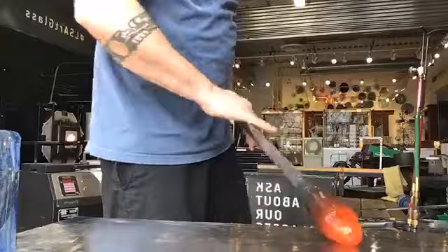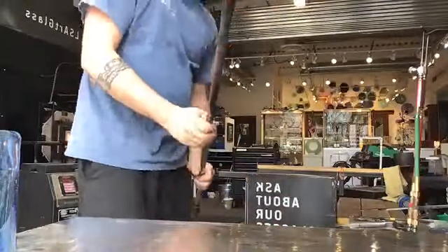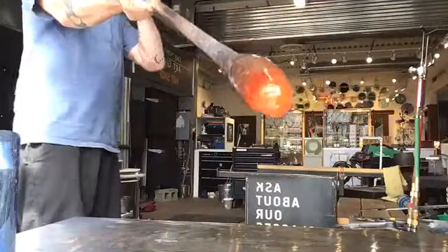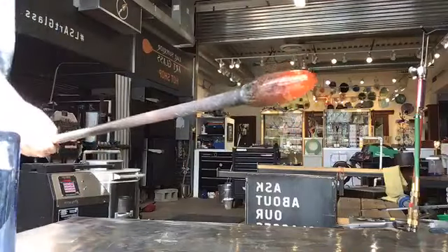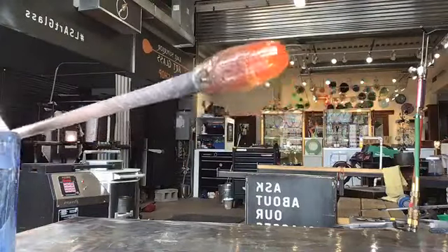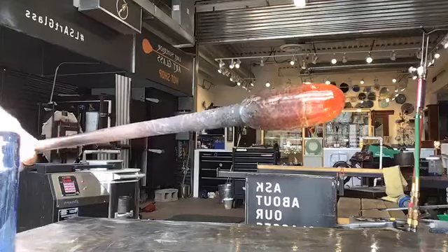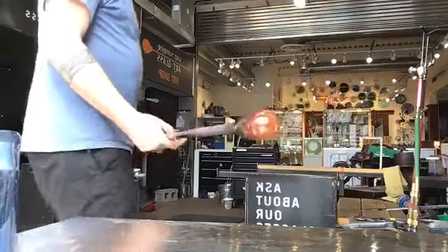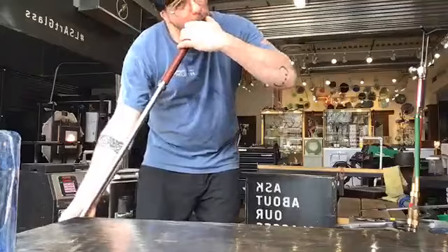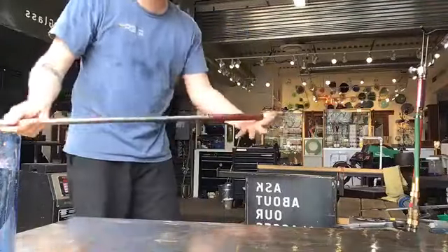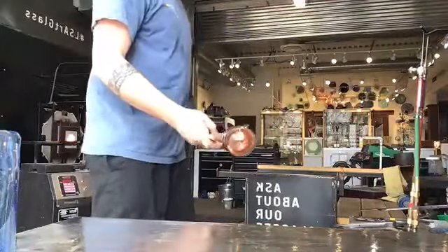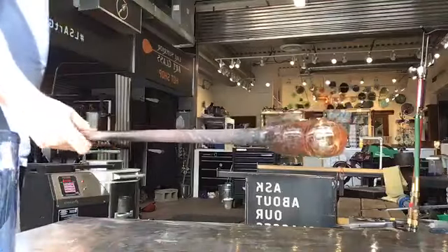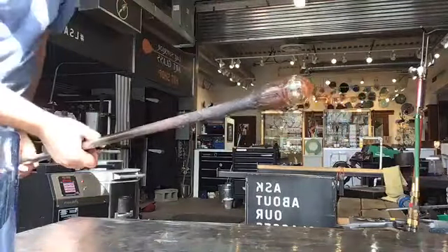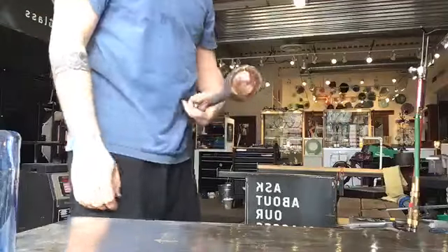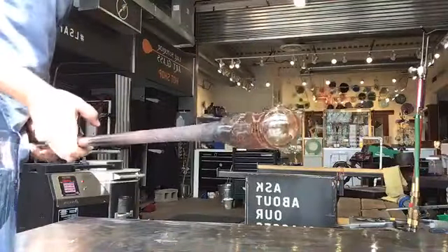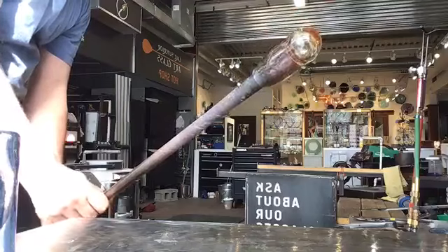Nice shape, nice and even. Go ahead and blow and cap. Should be able to see that bubble coming through the glass. I plugged. So the way I did that is I blew into the pipe and trapped my pressurized breath with my thumb. And so that pressurized air moves up through the pipe into the hot glass and expands our starter bubble. Because the heat was even, we have a nice even starter bubble.